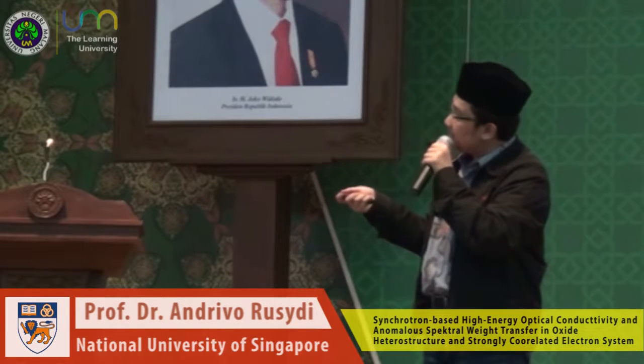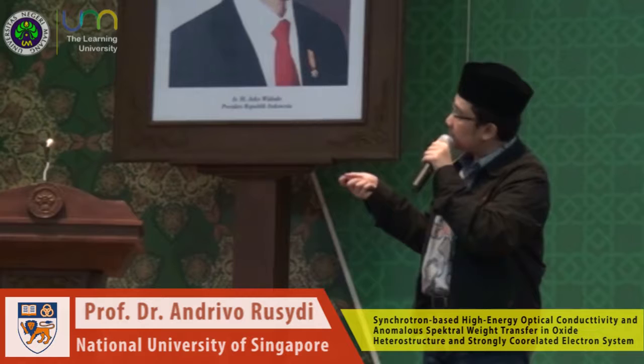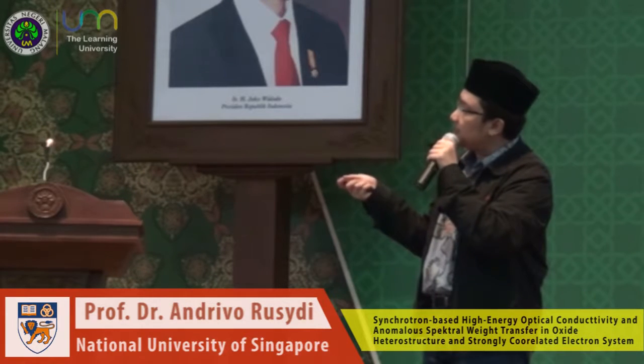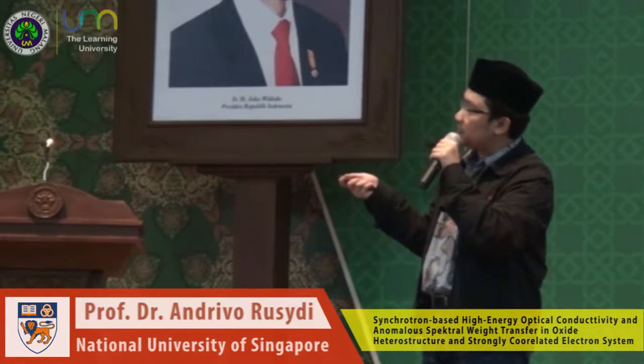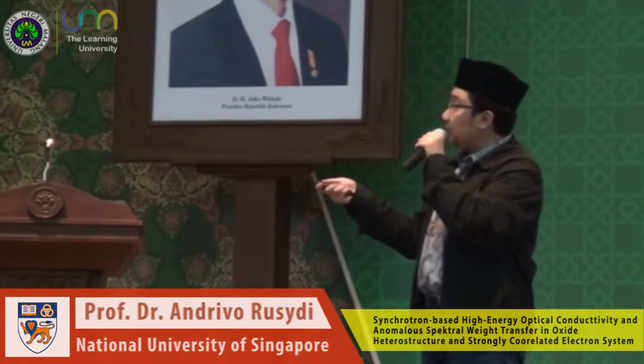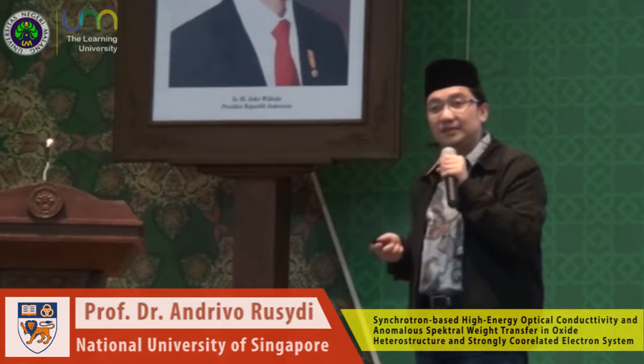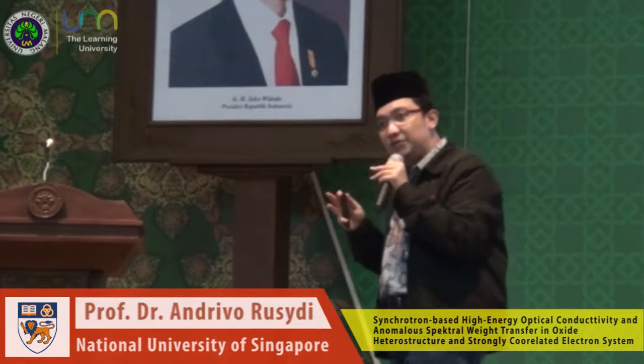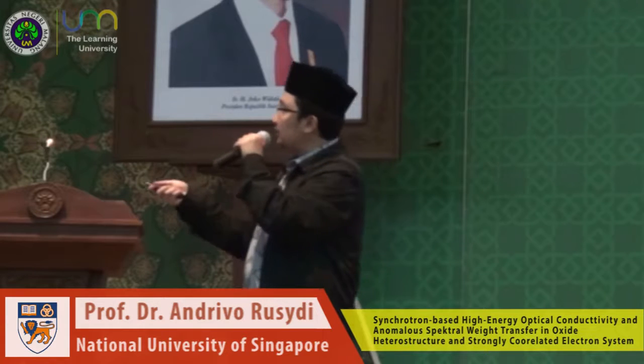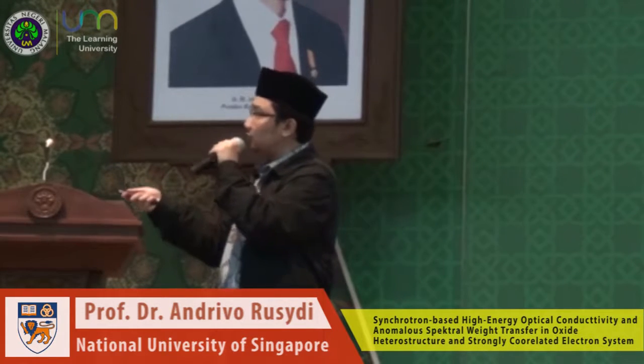What is really interesting is that if you look at this structure, there's a very sharp structure in the absorption part of the difference in the optical conductivity, and it changes dramatically as a function of temperature. And this structure was missing in all the experiments in the past. They never measured it. All the experiments were done below what is called 3 electron volts.